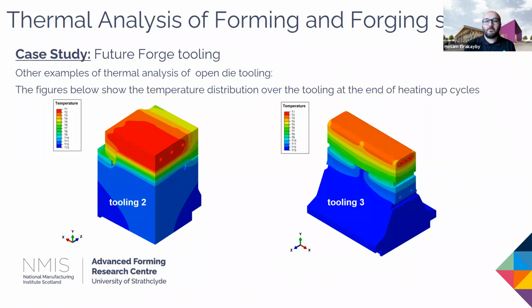So as previous example, you can see that we were able to maintain the temperature at the top surface as a targeted temperature for the forging process, while the bottom surface temperature is reduced for assembly of the press bed. In those 2 designs, we are using 2 different design concepts based on our experience and knowledge that helped us to reduce temperature at the bottom of the tooling.